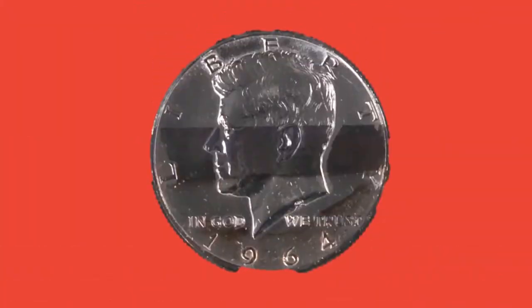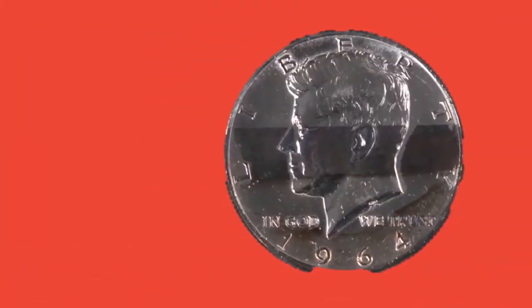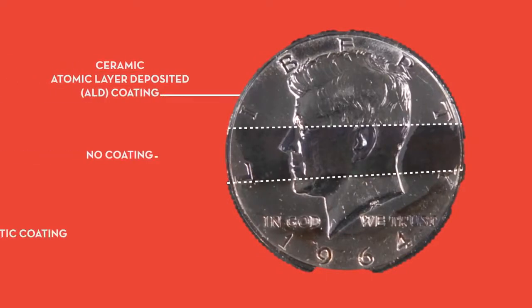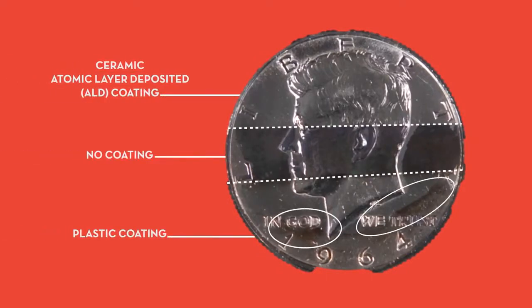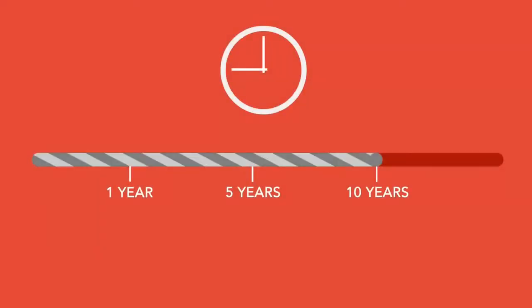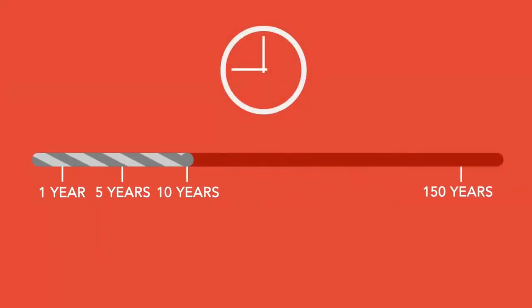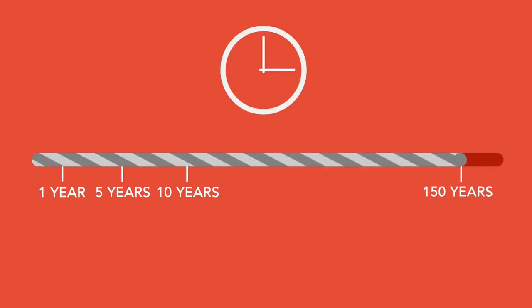In fact, when I did a blind study with art conservators, they were unable to distinguish between a silver coin with an ALD coating and one without. I found that the ceramic ALD films lasted 15 times longer than the plastic coatings. That's a huge improvement. For art conservators, this means that instead of every 10 years, they could wait 150 years before having to polish and reapply a coating.